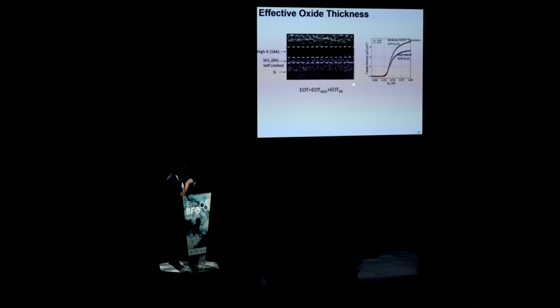That's what we get. But what we saw is, this is Intel's advanced transistors, EOT is 9.5 angstrom. Our transistors had an EOT of 6.5 angstrom. So you see that EOT has gone down, so capacitance is up, that you can see from here. But very interestingly, the EOT is smaller than the thickness of the SiO2, which means that for our high-K, the effective oxide thickness is negative. And that is happening because the ferroelectric is providing some kind of a negative capacitance in the entire stack. And so with that, we could then build transistors.